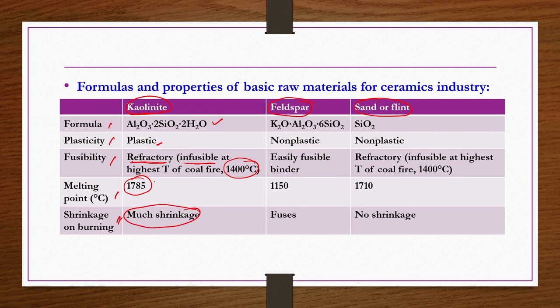From the thermal stability point of view, you might think that the melting point is very high and it is infusible even at 1400 degrees centigrade, so you take most of the raw material as kaolinite, let us say 80% kaolinite and the remaining 20% feldspar or sand. You may not get a final product. You may have a thermally stable product, but not a proper product, because on heating, kaolinite undergoes much shrinkage, which is not good. Okay, so feldspar.